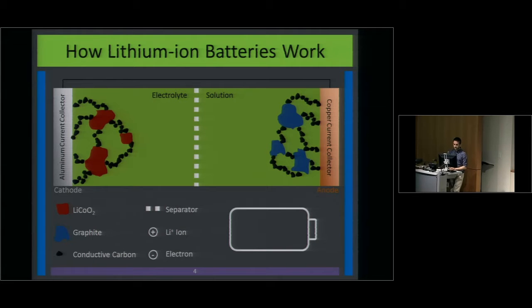When you charge a battery, lithium atoms dissociate from the lithium cobalt oxide into a lithium ion that's positively charged and an electron that's negatively charged. The lithium ions travel across the battery through the separator to the anode, and the electrons travel through a circuit, and they meet up in the graphite, and that charges your battery.